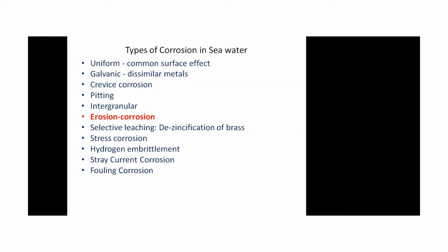where it is not only the sea water, but the sand is also there near the shore. It is causing wear of the components of the ship. Because sea water is already there, it is causing corrosion. But the sand particles and other particles present near the shore, because near the shore the depth of the sea is very less, so only there erosion corrosion is possible. So whatever hulls and seashore fixed structures are there, they are prone to erosion corrosion.